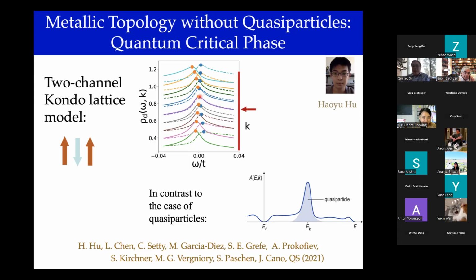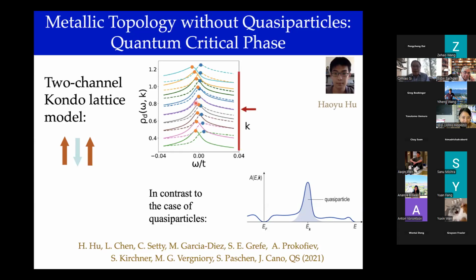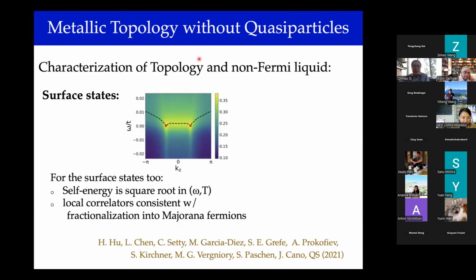And one could ask, how would one know? We can formulate a problem in terms of the eigenvectors of the Green's functions, and that serves as the analog of the Bloch functions, and see that the corresponding Berry flux, for example, is quantized, and that will have consequences for the bulk boundary correspondence. And in fact, that's one way for us to probe the topology, which is to ask whether there are surface states, which one would expect if the bulk state is topological.